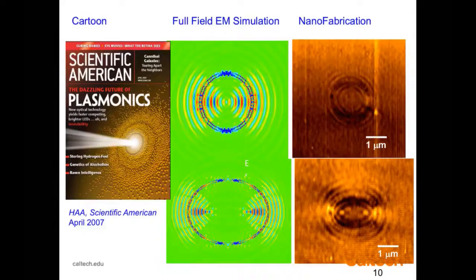And we decided, okay, this is a nice idea, but let's go into the lab and see if we can do this. So what we did was to take a silver surface, and then we coated that silver. We used the focused ion beam tool to make a groove in the silver surface here.